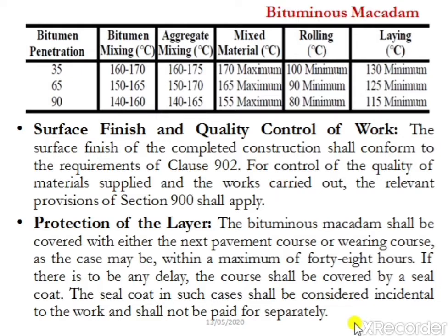The next process is protection of the layer. The bituminous macadam shall be covered with either the next pavement course or wearing course, as the case may be, within a maximum of 48 hours. If there is to be any delay, the course shall be covered by a seal coat. The seal coat in such cases shall be considered incidental to work and shall not be paid for separately.